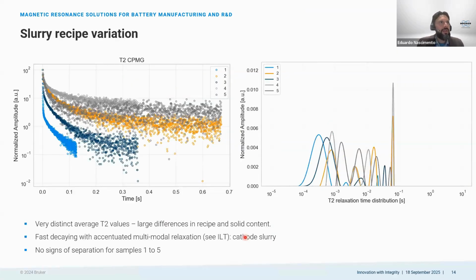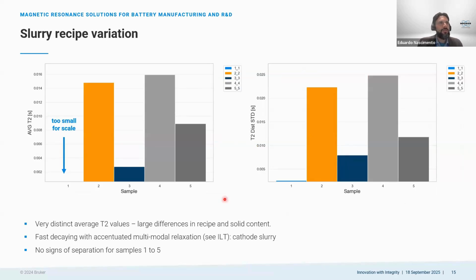So here again is a quick example of 5 different slurry recipes. They even have solid content differences. And of course, if you try to analyze this graphical data, it becomes quite complicated, and this is where this numeric value comes in handy, as you can see that all of them are all over the place. There was no intention here to have any correlation, the idea is just that if you have 5 different recipes, you will see 5 different numbers for that. And of course, if you are optimizing your process, you would like to see all of them at the same level.